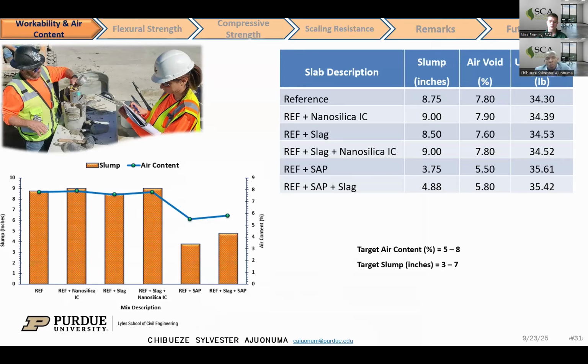And we noticed that the addition of SAP to the concrete mixes reduced the slump value, but all the concrete mixes we did were within the design target values. The addition of SAP reduced the slump, but this can be improved by the addition of a superplasticizer. For this project, no superplasticizer was used, but if you want to increase the slump, we can add a high range water reducer.